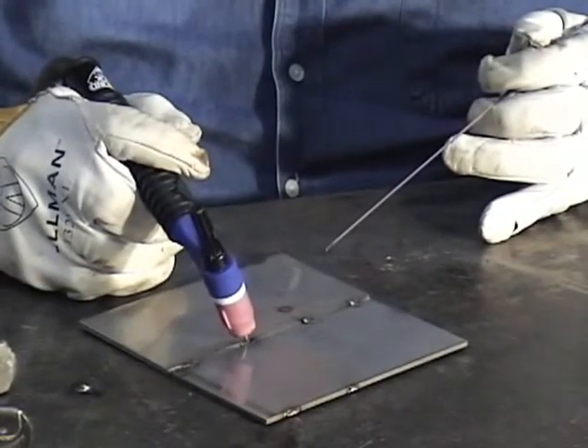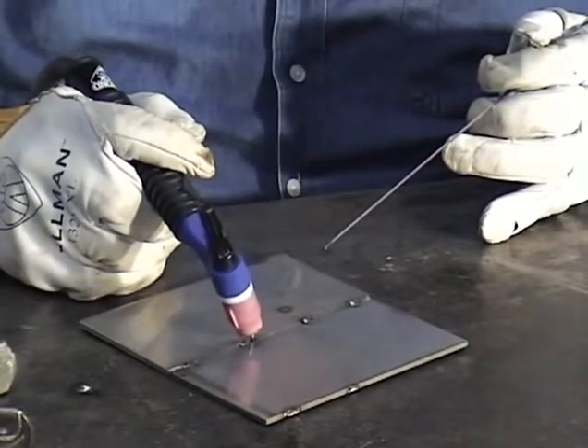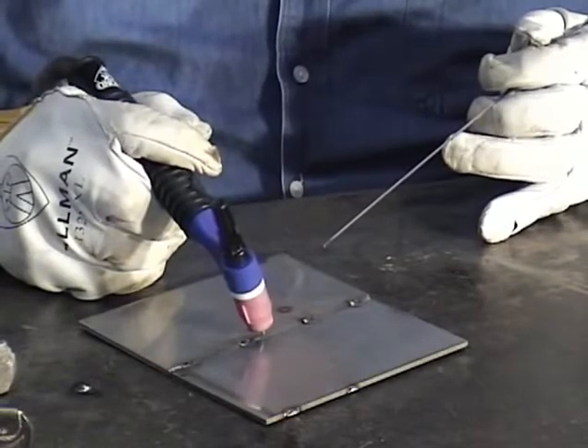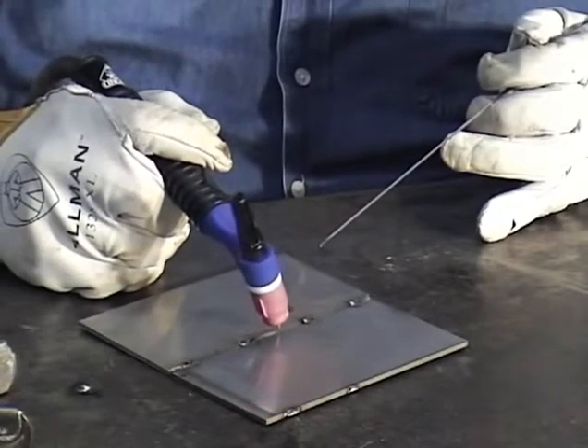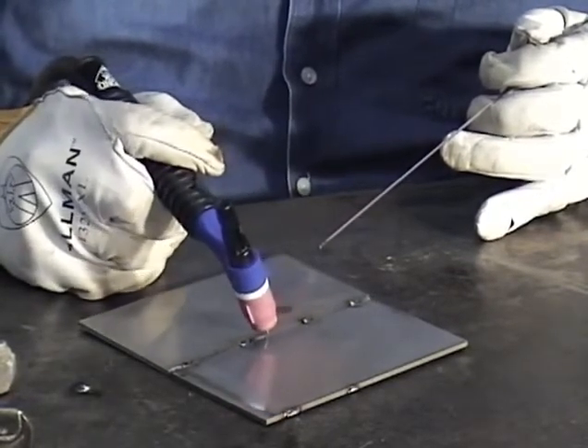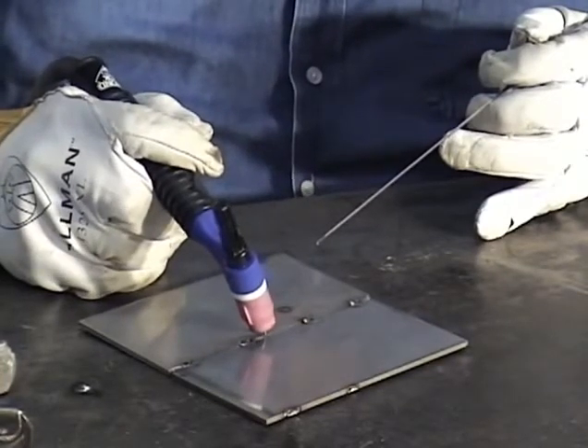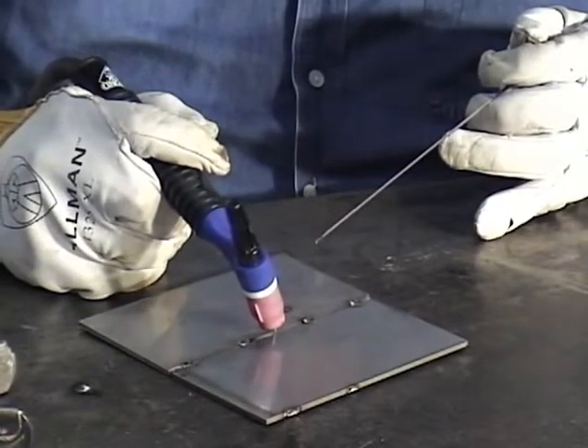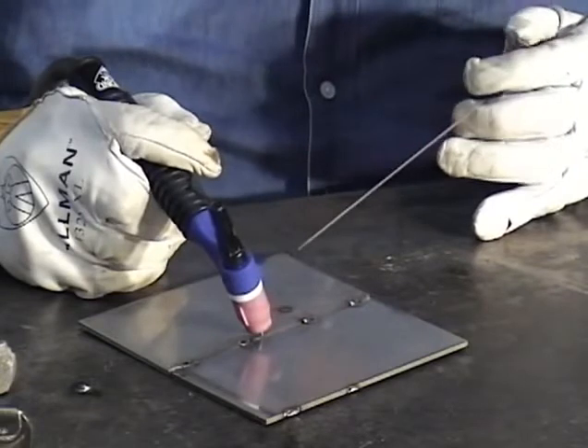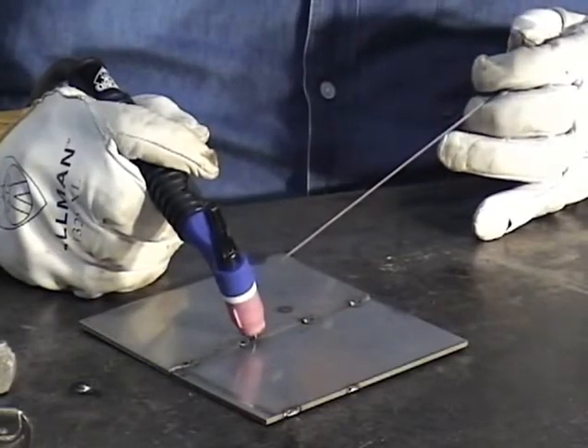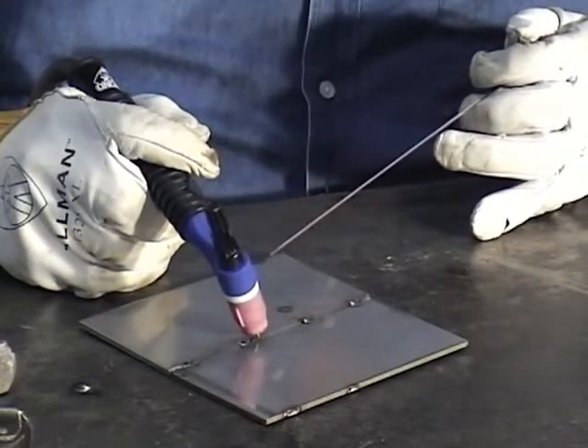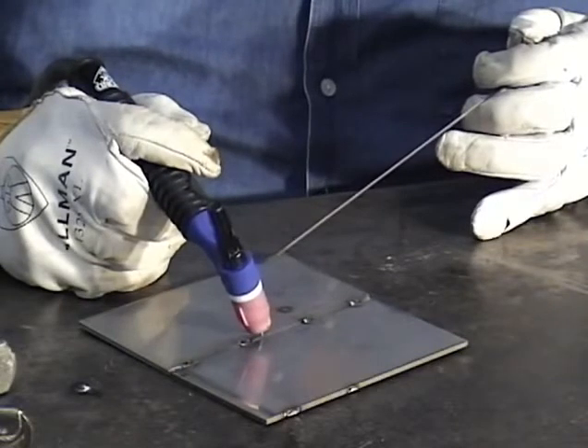Your tungsten should be about 50 thousandths off the material. 50 to 60 thousandths off the material as you weld down that plate, and you're going to be welding down the center of that joint, and you're going to make a solid root pass. And what you're looking for is liquid molten metal. You're not looking for a keyhole or any of that business. You're looking for liquid molten metal.